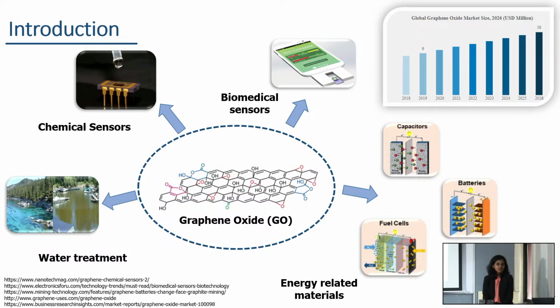This graphene oxide is a monolayer of sp2 hybridized and sp3 hybridized carbon atoms that are hexagonally arranged in the lattice. The basal plane of this graphene oxide is decorated with different oxygen functionalities such as hydroxyls and epoxides, and then carbonyls and carboxyls. Here hydroxyls and epoxides can be seen on the basal plane of graphene oxide, while carbonyls and carboxyls can be seen at the edges of the basal plane and the defects.